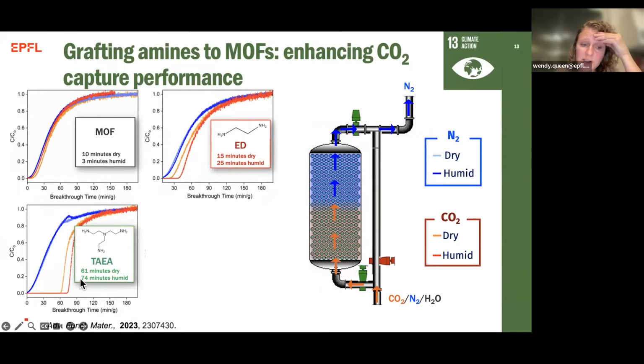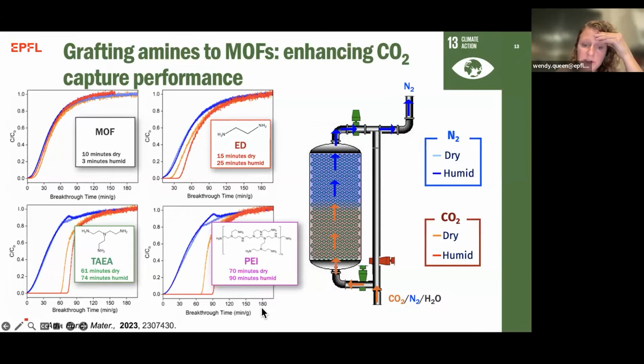TAEA has a dry separation of 61 minutes and then 74 minutes under humid conditions. And then finally, we see the PEI, which is our best performing material because we get the largest separation time between nitrogen and CO2, 70 minutes under dry conditions and then 90 minutes in humid conditions.